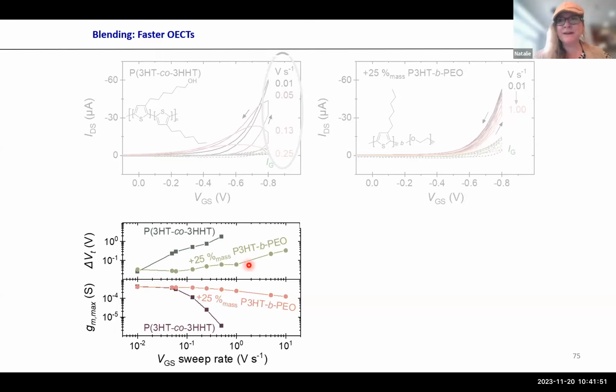Also, if you do stability measurements, so you put your films into water, the block copolymer helps to keep the device more stable, which makes sense because PEO at the end will still swell and sometimes mechanically disintegrate, versus when you have the block copolymer, it helps simply because the P3HT will not be affected by aqueous environments. Great, thanks. But in principle, it's doable if you just want to have a nice transistor that simply doesn't operate for a long time. Does that make sense? Yeah.